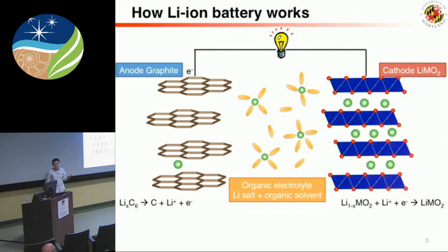Okay, so the disadvantage is that it doesn't work. Basically, I think the logic is this. If you look at the periodic table we showed, lithium is a one-charge ion, so when you cycle lithium, it only gets you one electron per lithium. If you use magnesium, you can get two electrons per magnesium. That's one of the big arguments: you essentially get more capacity.